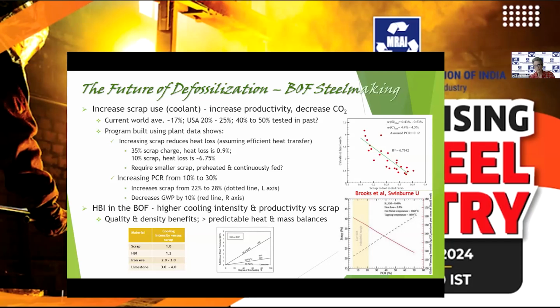Obviously, for the future, using more scrap would require smaller pieces of scrap, potentially preheated and continuously fed to the BOF. If you look at increasing the PCR from 10 to 30%, which is the bottom chart, and increasing scrap from 22 to 28%, which is the dotted line going upwards, you can decrease the global warming potential by 10%. And also HBI in the BOF is going to have a higher cooling intensity and productivity impact.